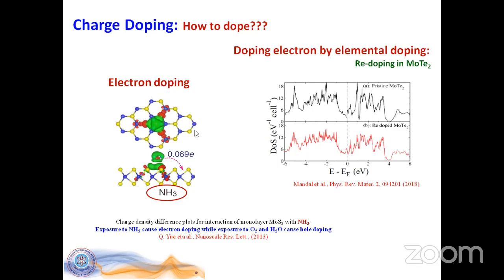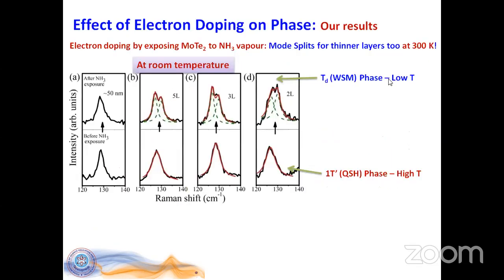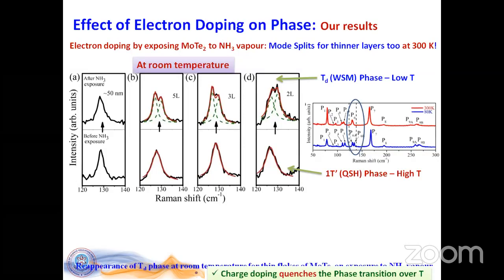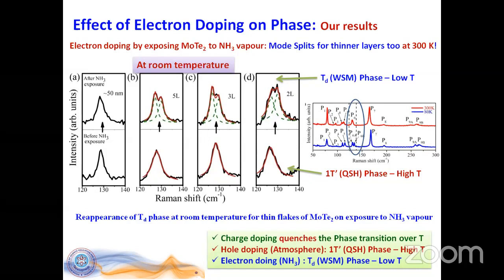And this is another example, by rhenium doping, which I'll show in a couple of minutes. Upon ammonia exposure, which we know electron dopes the system, we see the clear splitting of the single mode into two modes, even in very thin layers. Here is the 2-layer sample, 3-layer sample, 5-layer sample, and so on. Right at room temperature, all of them show the clear signature, and that establishes the other article as well. If it is electron doped, it shows the splitting, which is the orthorhombic phase. And if it is hole doped, it gets stuck in the monoclinic phase, which is what I showed in the previous data.